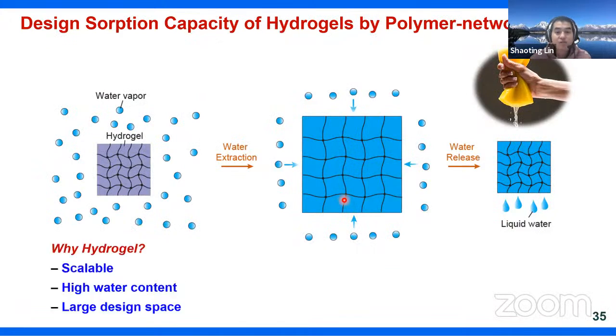So this is basically the process by which the hydrogel can harvest water from air. There are 3 benefits. Why can a hydrogel be beneficial? First, different from metal organic frameworks or zeolite, hydrogel is scalable. It's easy to manufacture in large pieces, and hydrogel contains high water content, which gives people confidence that it can achieve high sorption capacity. Second, hydrogel makes it possible to achieve a larger design space by manipulating the polymer-network architecture or engineering the functional groups. While this field is quite emerging, many high-profile papers have been published in the recent 5 years.